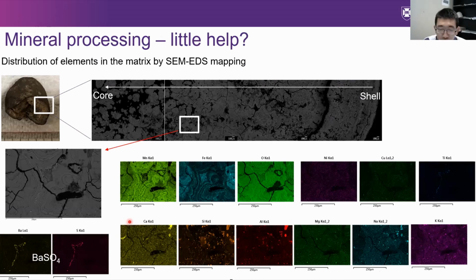So we are prepared for the deep sea mining. Then following the mining and the collection of nodules, the first step is mineral processing. Mineral processing is normally used to concentrate and upgrade the ores. However, from this SEM EDS mapping of the elements distribution, the nodule shows major manganese and iron, and also the critical metals nickel, copper, and titanium, and some other impurity elements.